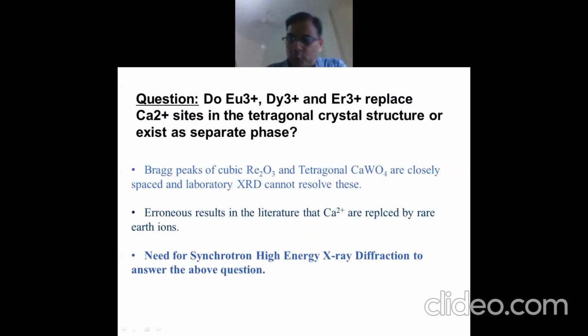So the unresolved question in these materials is, do europium, dysprosium, and erbium ions replace calcium ions in the tetragonal crystal structure, or do they exist as a separate cubic phase? Europium oxide and the other rare earth oxides have a cubic crystal structure, whereas calcium tungstate and calcium molybdate have a tetragonal crystal structure. Many people have done X-ray diffraction studies on these materials.